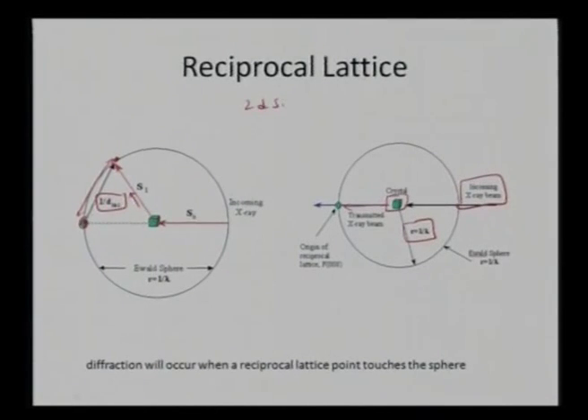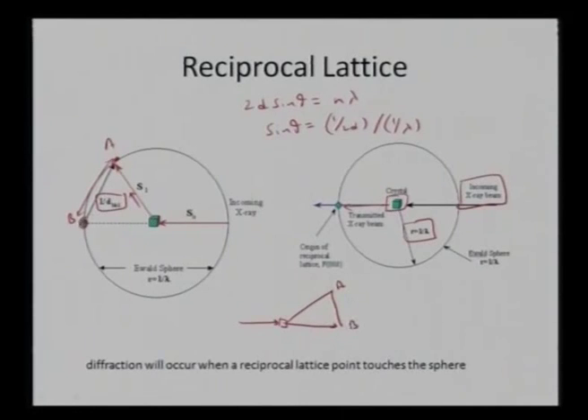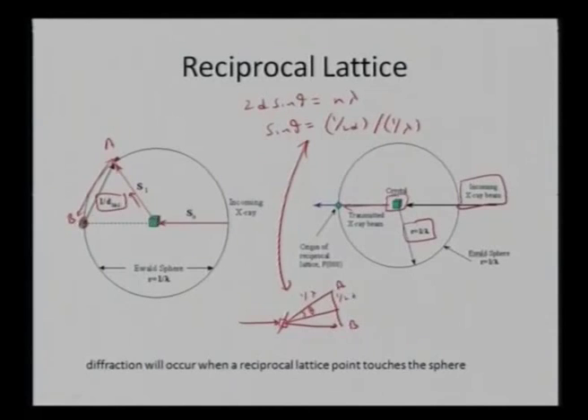From 2d sin θ = nλ, I can define sin θ = (1/2d)/(1/λ). I can see that if my incident beam interacts with the crystal and goes away, everything falls on the Ewald sphere. Taking two particular points a and b, half of the angle is my θ. What I am seeing is 1/(2d) and 1/λ, and that is what is now shown from this equation. Crystal planes oriented in a certain direction give θ, and 1/λ, with everything falling on the Ewald sphere.